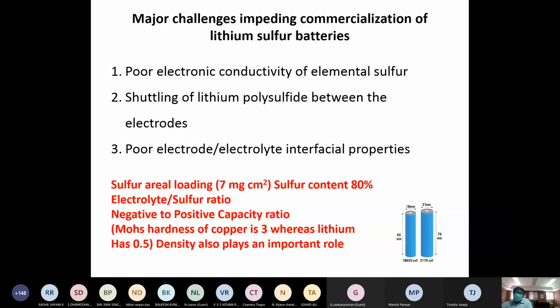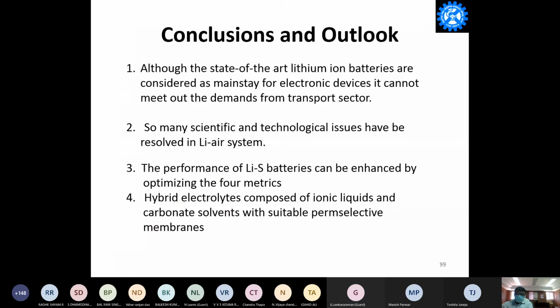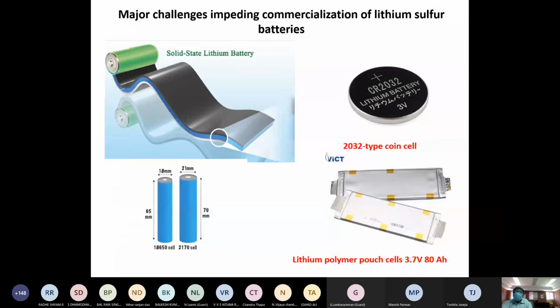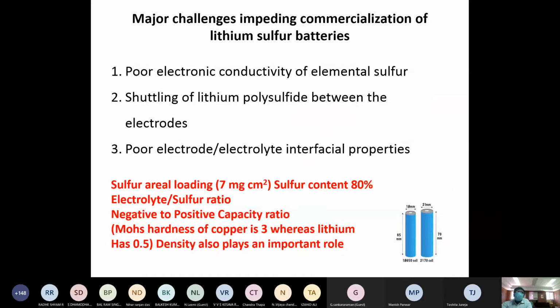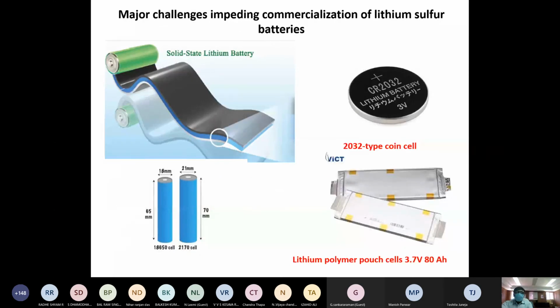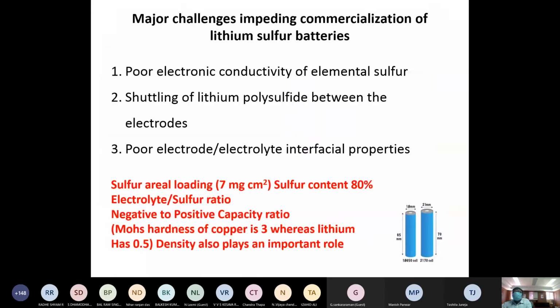But the problem is, when it is commercialized, it can be commercialized only in the form of pouch cells. It cannot be commercialized in the form of 18650 because for lithium sulfur batteries we are using only lithium metal as anode. But the problem is the hardness of lithium is very low, 0.5 only, whereas copper is 3. So we cannot roll the lithium foil for commercial applications. That means it cannot be available in the form of 18650. It's a major issue of lithium metal.